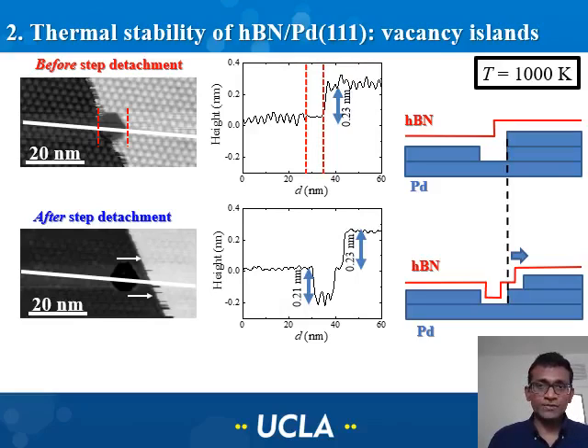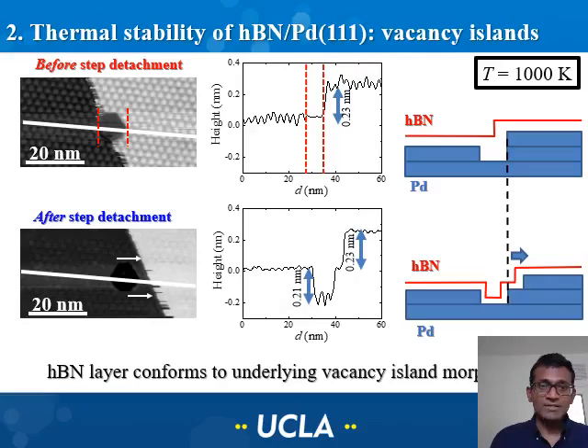in the surface. Okay? As the vacancy island detaches and the step moves away from the vacancy island, we then measure the step heights that correspond to the vacancy island plus that of the step edge. Okay, so now we can clearly see that we have a 2 atom deep hole, a vacancy island on the terrace, and a step edge. Whereas when the island was pinned to the step edge, we only measure the step height as if it's a monoatomic step, meaning that the hexagonal boron nitride is tightly wrapping the vacancy island.